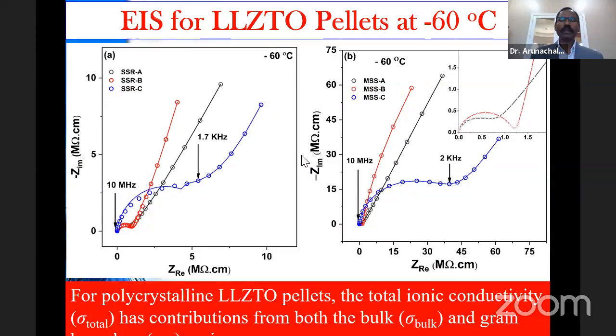In order to understand the conductivity and also the conduction mechanism, impedance measurements were carried out at various temperatures, from minus 60 degrees Celsius all the way up to room temperature, 25 degrees Celsius. That was done mainly to understand the Arrhenius behavior and to estimate the activation energies. The total conductivity certainly comes from both bulk and grain boundaries. This is for the pellets made by solid-state reaction and the molten salt.